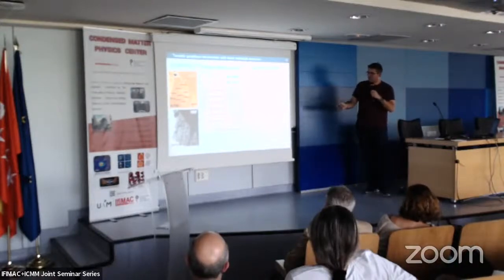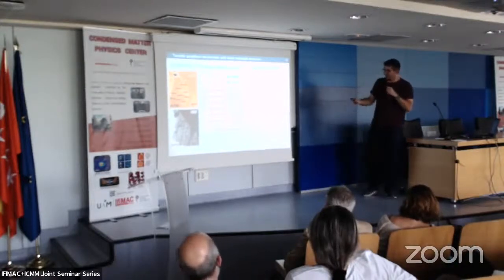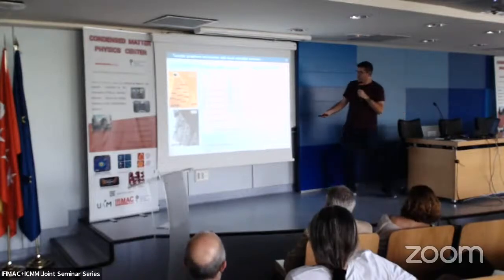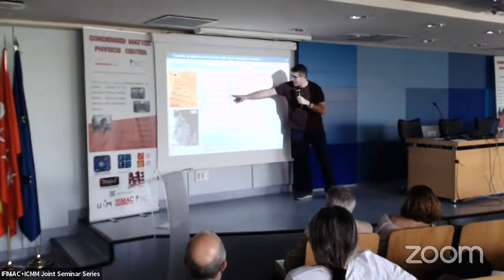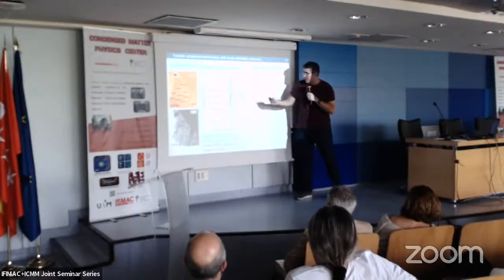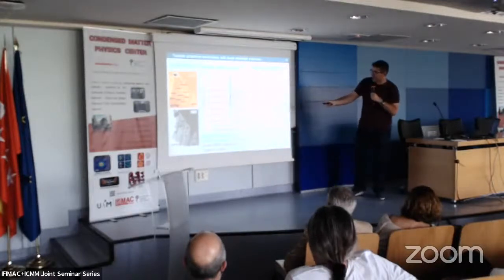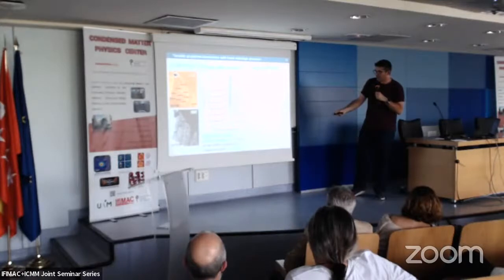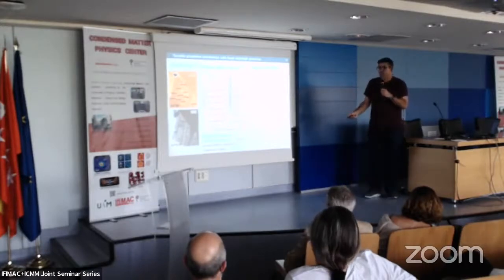Here are some examples. What we can see here in a first site is that the pristine peak, which is this one, is now centered in the blue line. But the peaks at higher pressures are all shifted to the right. You see all of them appear at the right of this blue line. So they are shifting toward lower binding energies. This is telling us that the Fermi level is shifting towards the valence band, as we already knew from KPFM. And also, this is due to this p-doping effect. Okay, nothing new in here now.